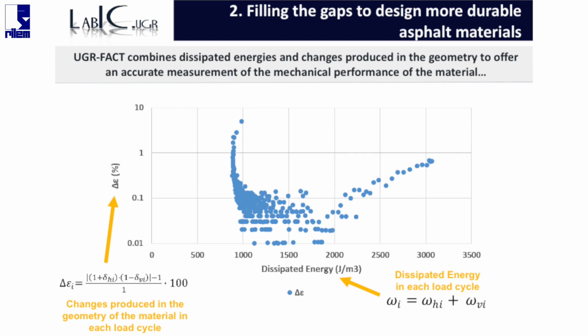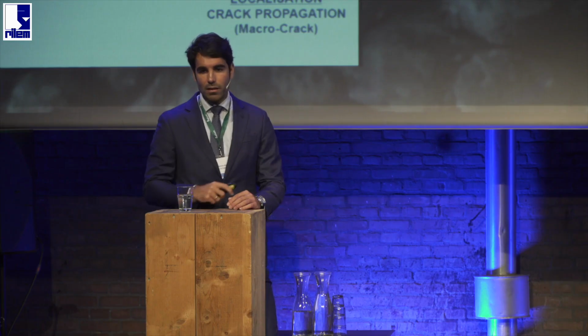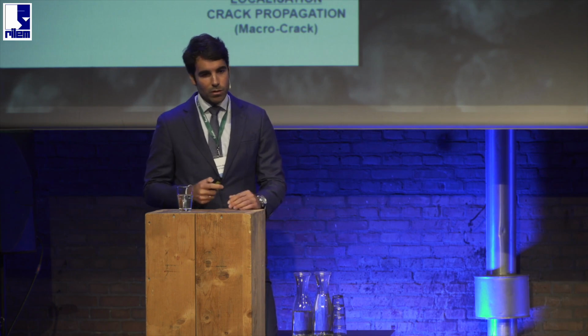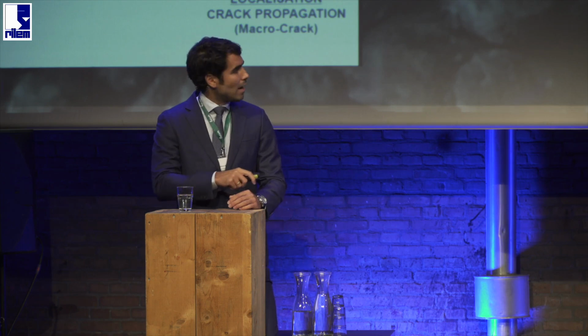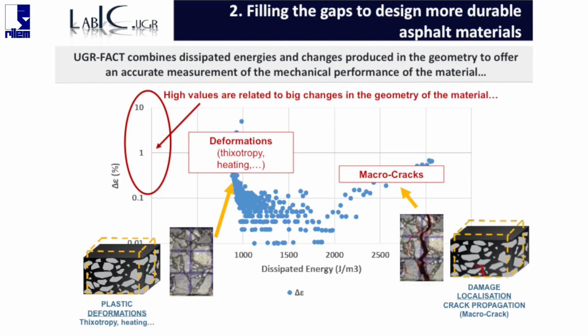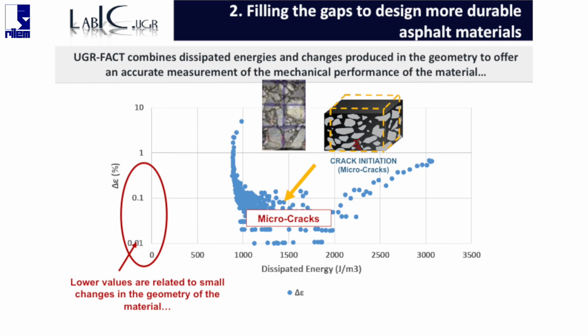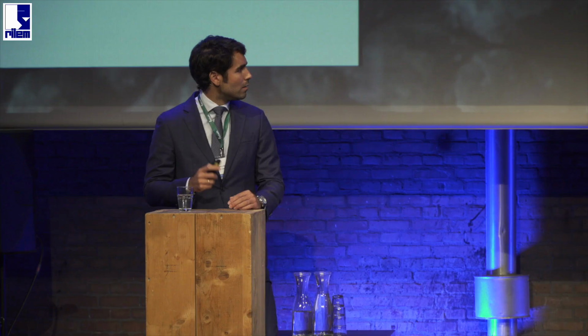So, as I told you, combining these 2 parameters, we can have an accurate measurement of the real mechanical response of this material. For this purpose, we put in the x-axis the dissipated energy, and on the y-axis the change in the geometry. So when we obtain big change in the geometry of the volume, that corresponds at the beginning of the test to plastic deformation or other viscoelastic phenomena, and at the end of the test to macro cracks. And when we obtain low values of this change on the geometry of the volume, we are going to have a stage that microcracks, small variation of geometry, are producing inside the volume.